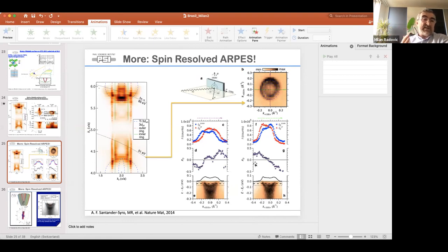While spin is a direct measurement, you are really taking the electron, and this electron comes to the hemispheric analyzer. So this is already defined by the energy, and then you start to look at the spin. They are accelerated, go to the foil, and then scatter from the foil in a different direction depending on the spin, and that electron was already in the system. But here, you might induce a kind of spin structure by the light, which is also okay, because this is a way to manipulate the system.